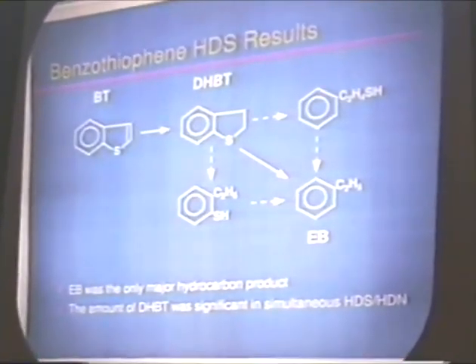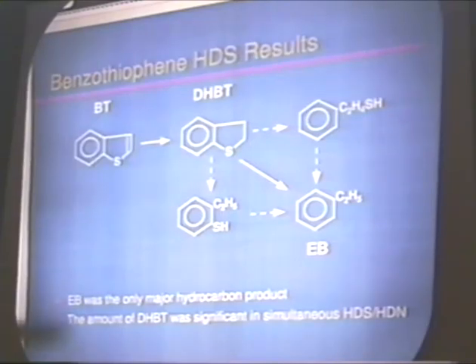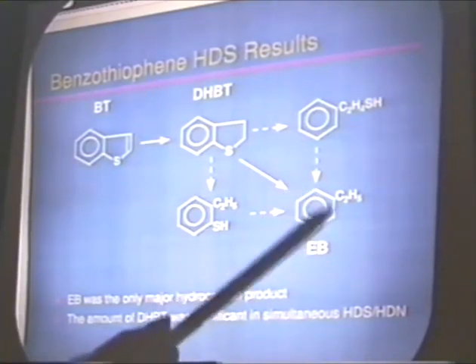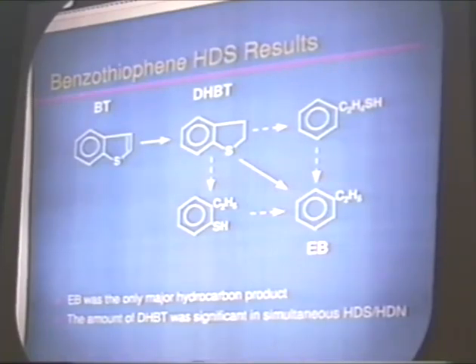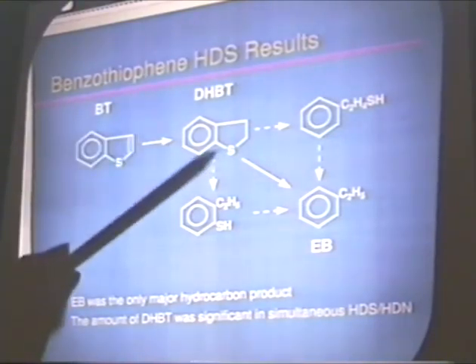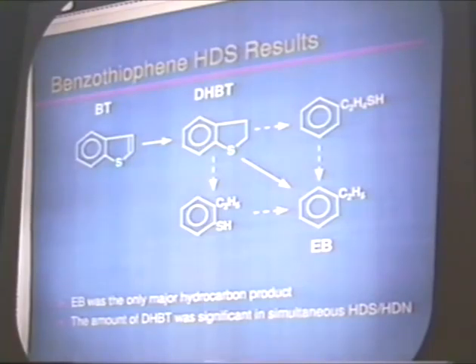Based on what we have observed during these experiments, we have come up with a suggested network for benzothiophene hydrodesulfurization, which is relatively simple. The major product that we observe from benzothiophene HDS is ethyl benzene. At some conditions, there is dihydrobenzothiophene present as an intermediate, and this leads us to suggest that before the sulfur hydrogenolysis takes place, the heteroatom ring has to be saturated. Also, the fact that among the hydrocarbons that we obtain, almost 99% is the unsaturated hydrocarbon, in this case ethyl benzene, suggests that we don't have to have the benzene ring saturation before the desulfurization takes place.